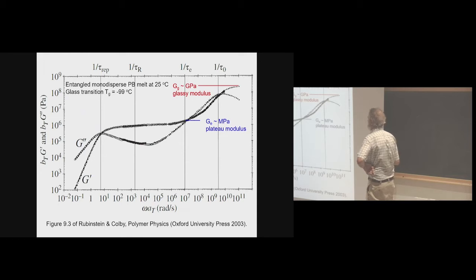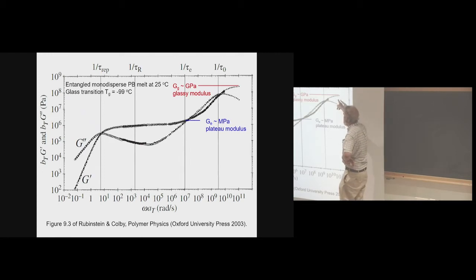So, right, here we see a more complete spectrum. The previous data were just isothermal data, but now I'm taking data at a lot of different temperatures, including temperatures that are very close to the glass transition, and making what's called a master curve by time temperature superposition. But you can see oscillatory shear can be very, very powerful, because at least I can pretend that, at 25 degrees, if I had a rheometer that could go to 10 to the 10 radians per second, good luck with that, maybe I'd see the glassy modulus, right?